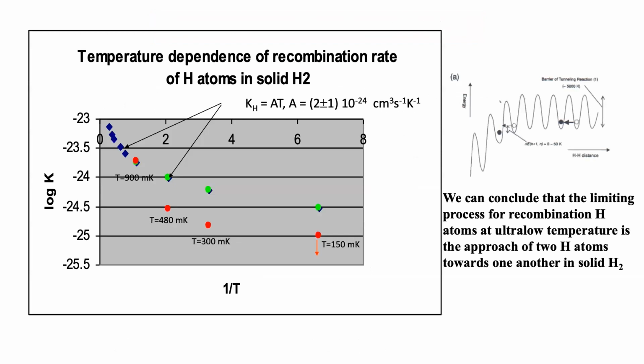If you place these points on the curve, you see at high temperature the dependence is proportional to temperature, but at low temperature it's much slower. So we conclude that this supports a mechanism due to tunneling, and the reduction of the recombination rate is due to increasing mismatch of the energy levels of the atom in the closest lattice sites.